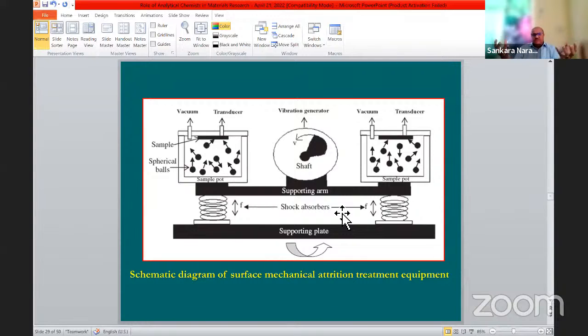We have two chambers, and inside, the samples are placed on top of the pot, and we put in steel balls. This is a stainless steel sample, fixed, and we put steel balls in the chamber, and it vibrates at a particular frequency, 50 hertz. So there will be rapid, random movement of the balls. The balls jump up and down and directly impinge on the top surface of the metal, and that induces plastic deformation. So this process induces plastic deformation, and there will be a change in the microstructure of the material.